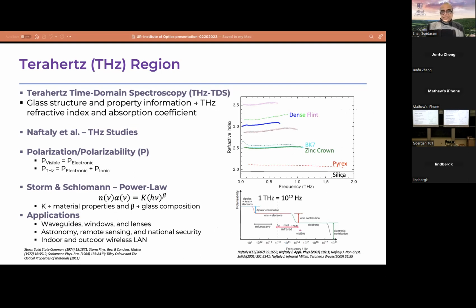Another thing I want to point out is in material science, again, the terahertz properties all depend on the polarizability of ions present in the glasses. Polarizability, as you know, in the visible range is predominantly to do with the electronic polarization. But when it comes to terahertz properties, both electronic and ionic contributions contribute to the property we are measuring. And then we were looking at the literature. There is also a Storm and Schlomann power law. They come up with a product of refractive index and absorption coefficient as a function of frequency that can be equated to a material property K with an exponent of beta, which can be tied to glass composition.